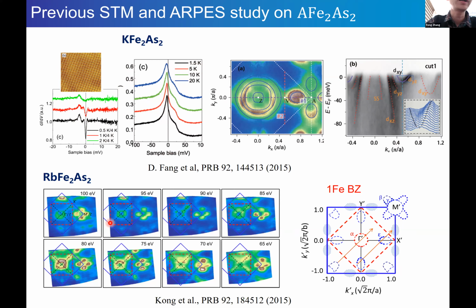And there's one ARPES study on the rubidium 1-2-2 system. But compared with the potassium one, the data is not as clear. They only observe a single hole pocket at the gamma point, and they claim it is more consistent with the single-iron, unfolded Brillouin zone, because the interlayer spacing is larger in this system. Maybe its folding is weak.